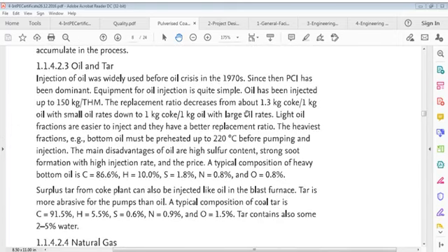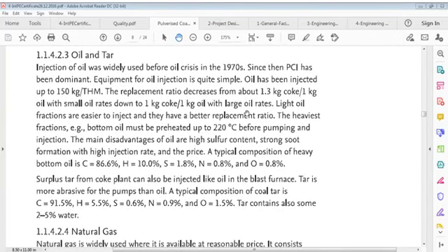Oil and tar. Injection of oil was widely used before the oil crisis in 1970. Since then, pulverized coal injection has been dominant. Equipment for oil injection is quite simple. Oil has been injected up to 150 kg per THM. The replacement ratio decreases from about 1.3 kg coke per 1 kg oil at small oil rates, down to 1 kg coke per 1 kg oil at large oil rates.